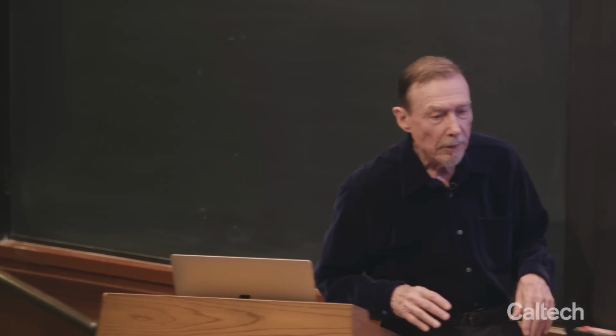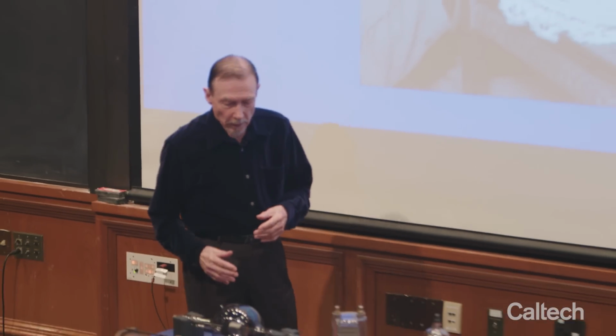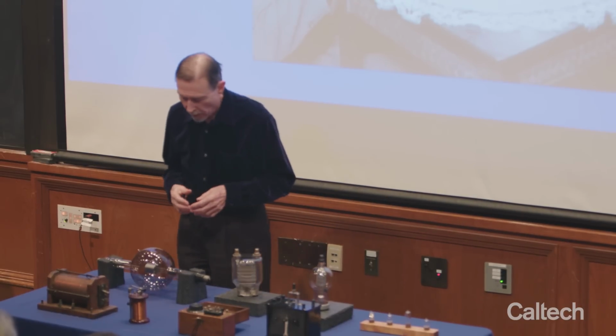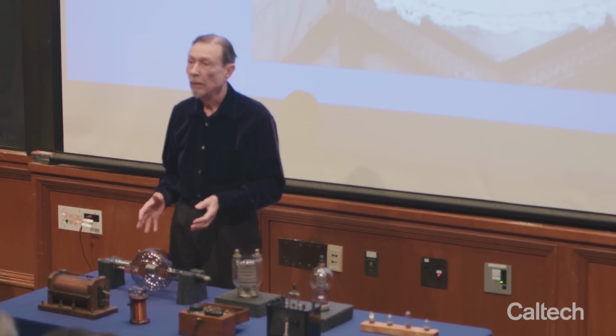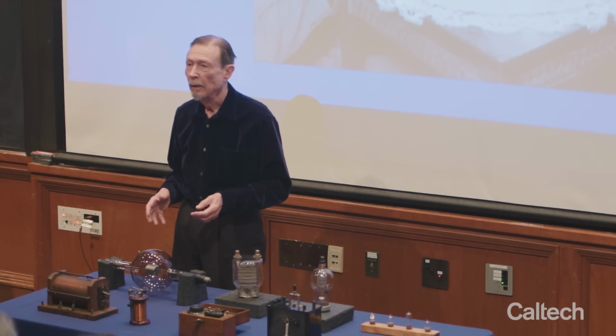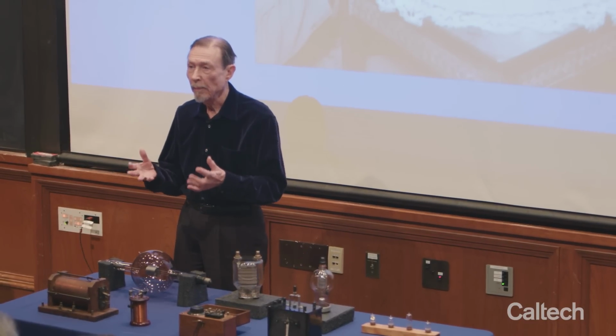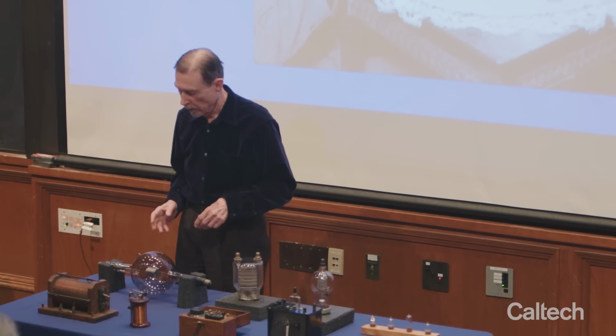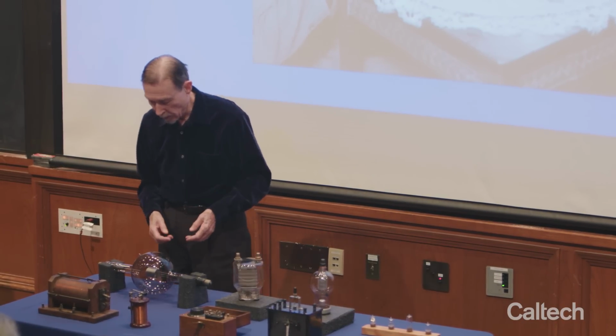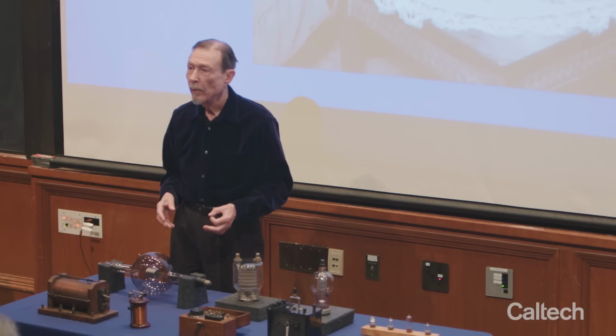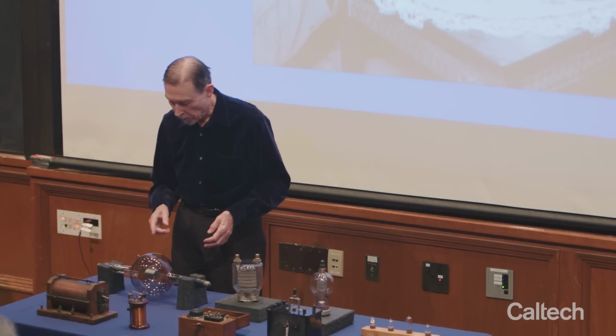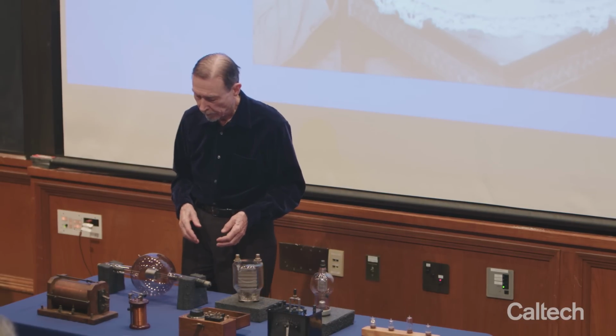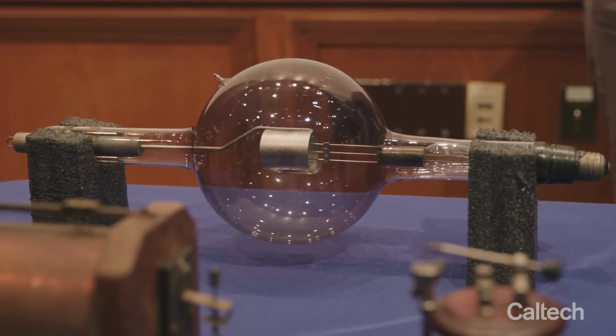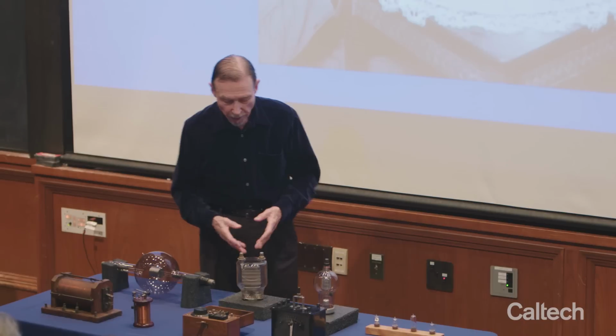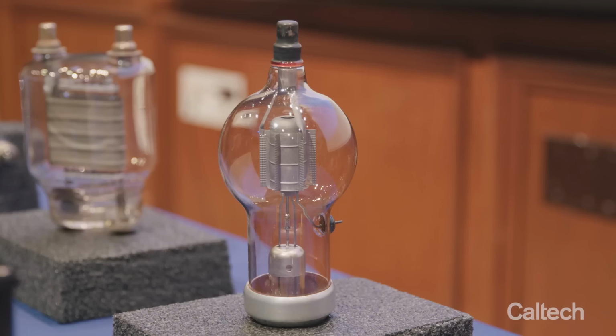And so it's very interesting. Irving Langmuir at General Electric really figured out how to make the modern high power transmitting tube. Because for a transmitting tube at high power, you had to have high currents and high voltages. This is one of the very earliest commercial transmitting tubes. It's called a GE Kenotron. And this was rectifying voltages up to 100,000 volts. And here's some of the other early tubes. This is the first transmitting tube that was manufactured here on the West Coast.